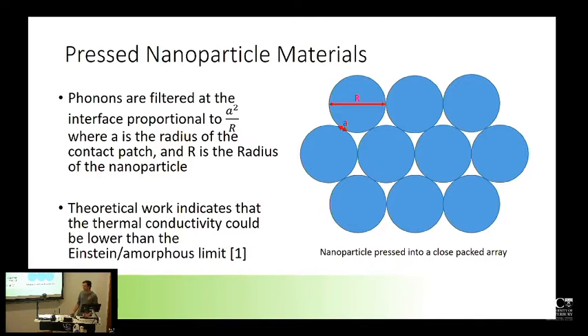And so you have phonons which have a certain wavelength between the radius of the nanoparticle down to about the constriction. When they are travelling through this constriction, they are sort of filtered proportional to the area of the constriction relative to the radius of the nanoparticle. So in theory, this can reduce the thermal conductivity of this material down to extremely low levels, below what's known as the Einstein or amorphous limit, which is supposedly the lower limit of what the thermal conductivity of a material can reach at a given temperature.